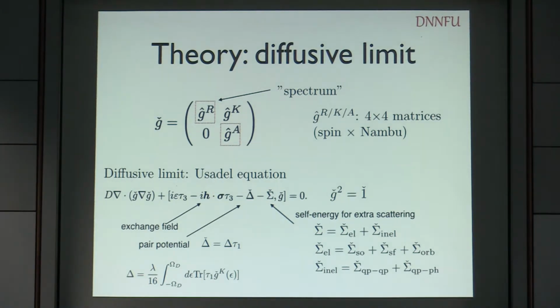By the way, we don't usually need to solve the self-consistency equation as such, except in the next example that I will show in a moment. And then we need to include all kinds of scattering effects, which are encoded in the self-energies. Here we have both elastic and inelastic scatterings, those related to spin-orbit and spin-flip terms, and some inelastic terms like electron-electron and electron-phonon.